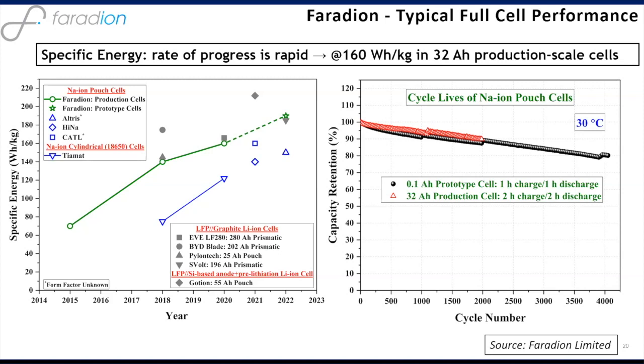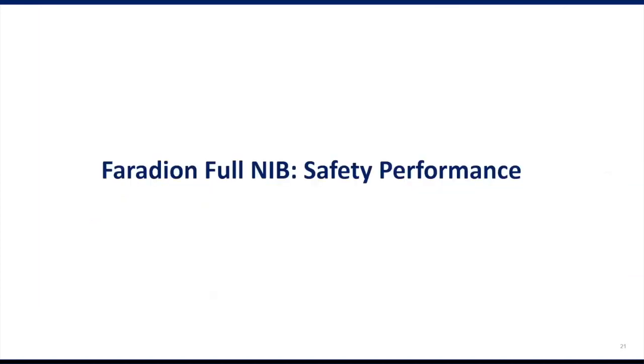And then on the right-hand side of this chart, we're showing the cycle life. Here we're charging and discharging prototype cells and production cells running at pretty high rates. And you can probably see here that we're out to 4,000 cycles, and that's still above 80% of the original discharge capacity. That puts us similar, I think, to really good graphite LFP cells in the lithium ion space.